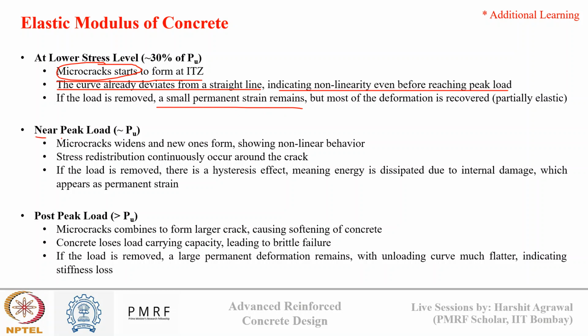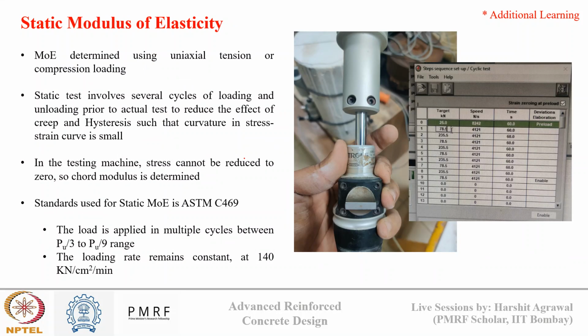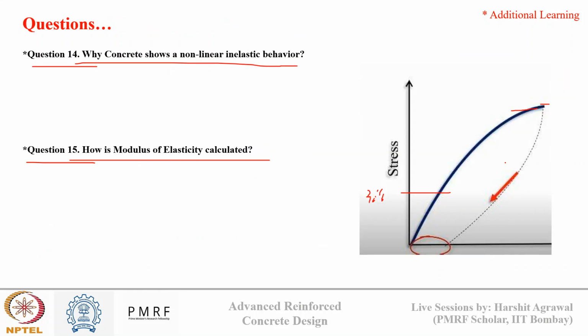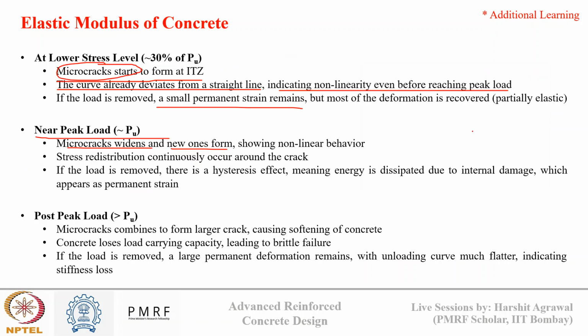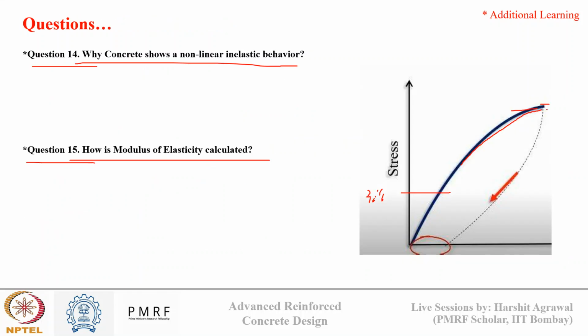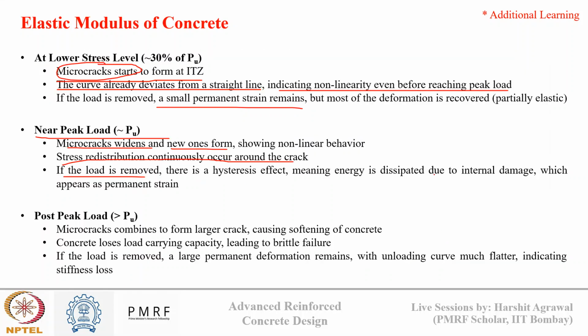As we near the peak load, what will happen? These micro cracks widen and they form new ones. So there is more non-linearity in the concrete because of the growth of the micro cracks. Stress redistribution continuously occurs around the crack, and if load is removed, there is a hysteresis effect. So you see here, when load is removed, there is a hysteresis effect. There is a permanent strain in the system.